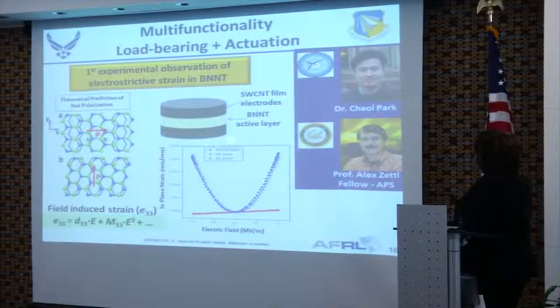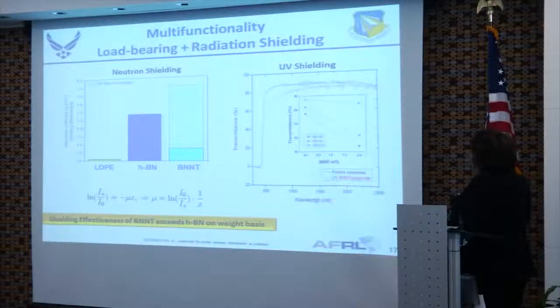Park has used what he likes to call his Oreo cookie configuration to actually measure the electroactive properties of this, sandwiching a boron nitride film in between carbon nanotube electrodes. And he's looked at the electrostrictive strain of these materials, and also here the linear relationship, which is the D33, the piezoelectric coefficient of these materials. And there's much more of this characterization to come, but it shows the potential for, in this case, load-bearing plus actuation.